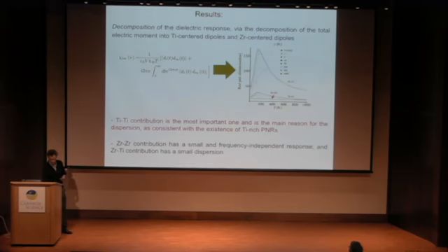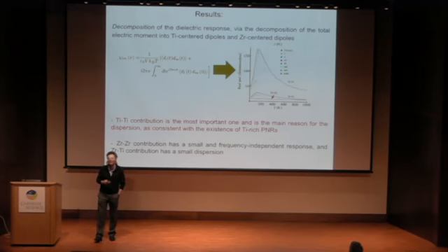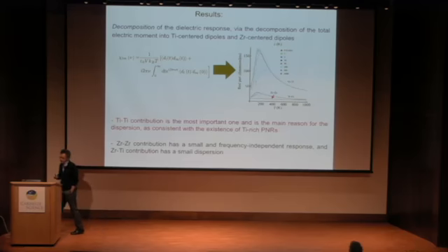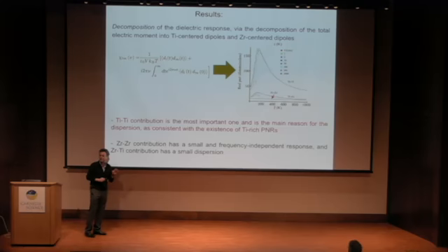and we mimic quite well the relaxor behavior. As I told you before, we not only wanted to see the dielectric relaxation, we wanted to have an idea what causes it and if we can further understand it. And in fact, a real beauty of simulations is that you can realize it by looking at the formula of this dielectric response. As I told you, this is basically an autocorrelation function between the total dipole at time 0 and the total dipole at time t. But in BZT, there are two contributions to the total dipole, one coming from the titanium sublattice and one coming from the zirconium sublattice. So in the total response, you have three parts.